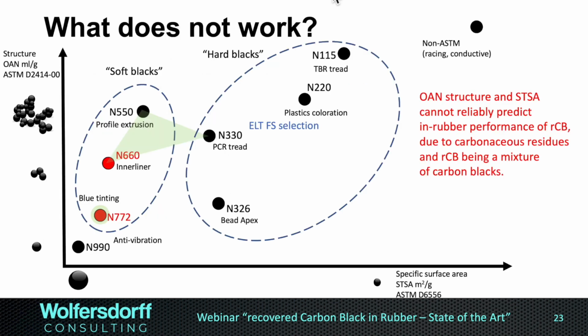Now, let's look at what does not work. Because for furnace carbon black, and we'll talk about furnace carbon black a little bit deeper in a moment when we get to rubber applications, what is required from a furnace carbon black is also required from a recovered carbon black. For furnace carbon black, the rubber performance can be very, very well estimated just by looking at the structure and the specific surface area.